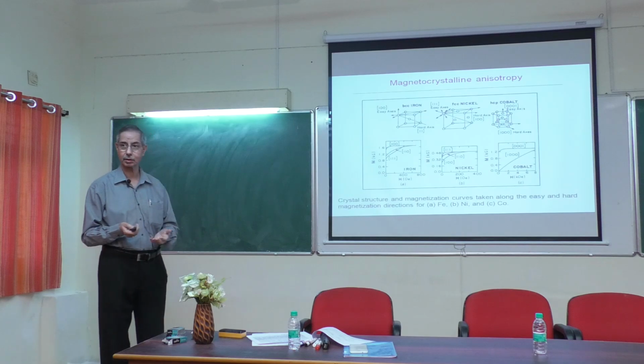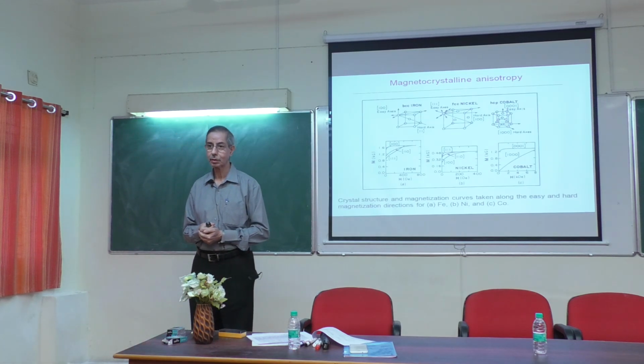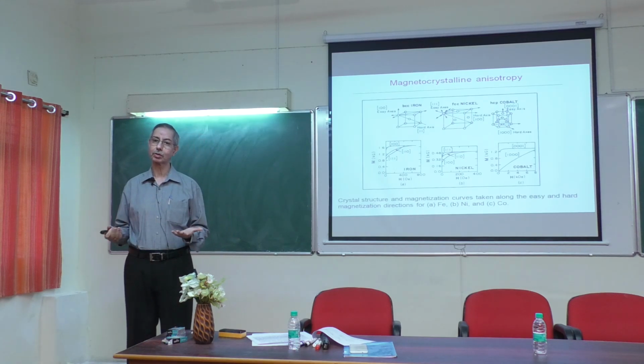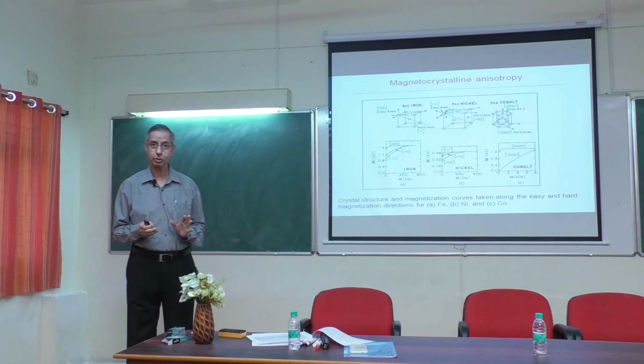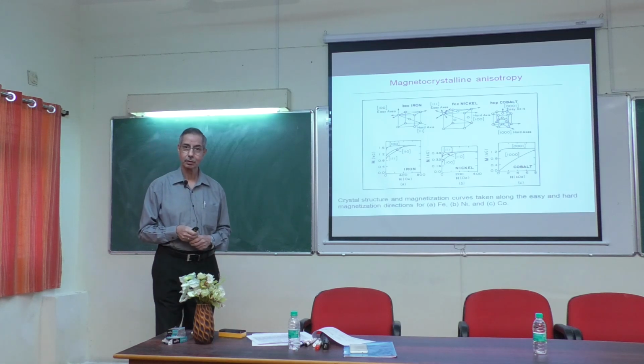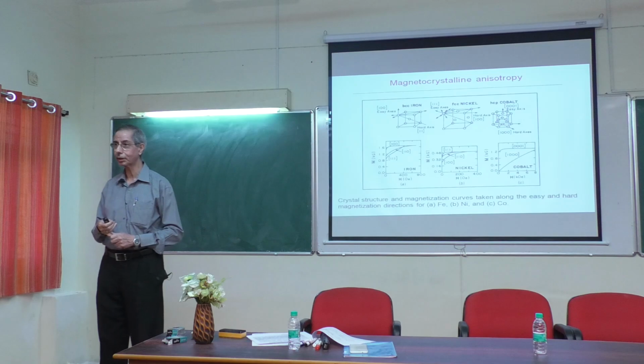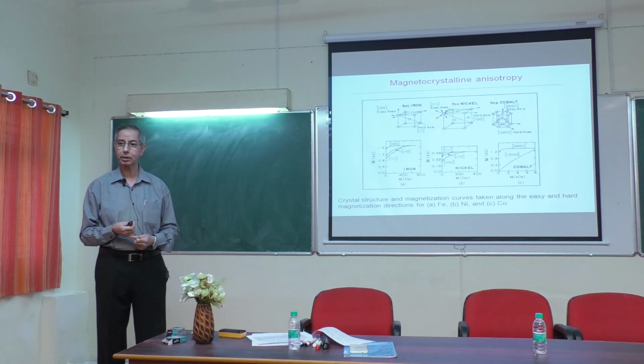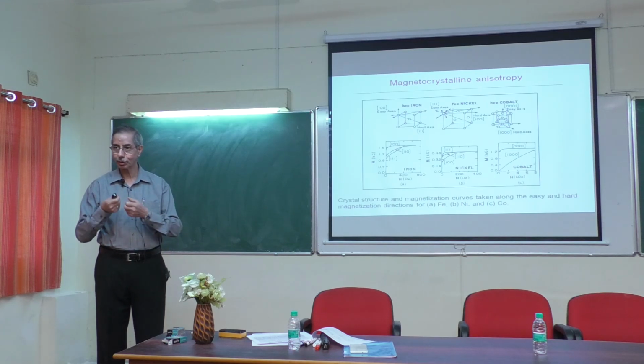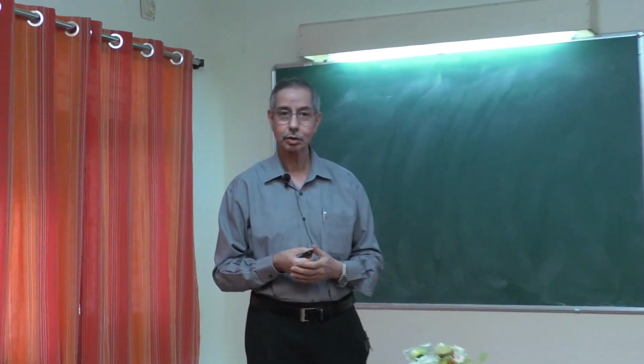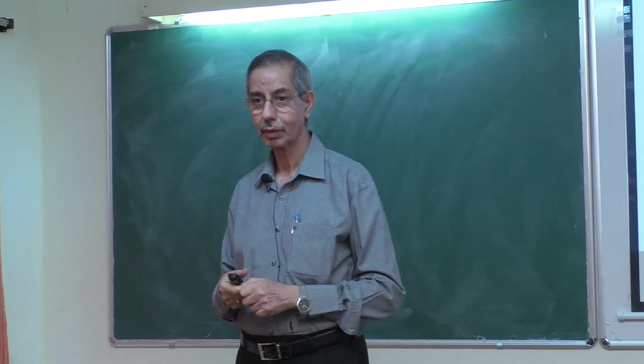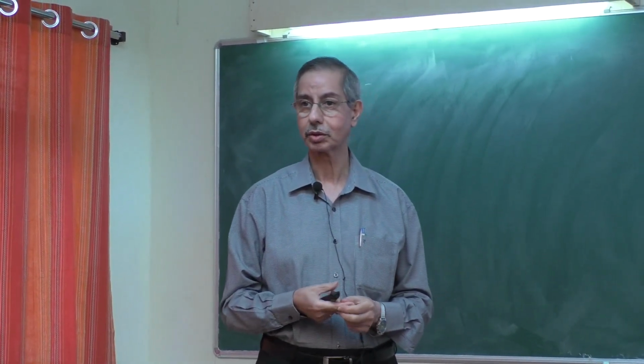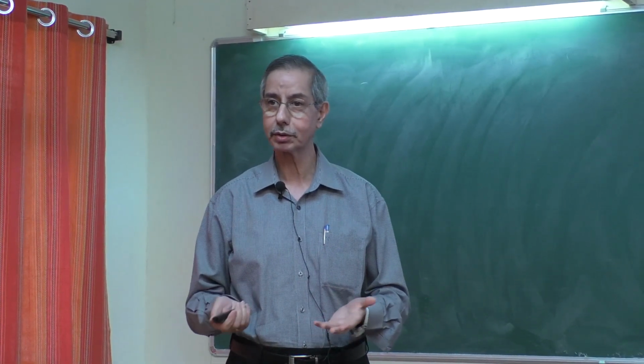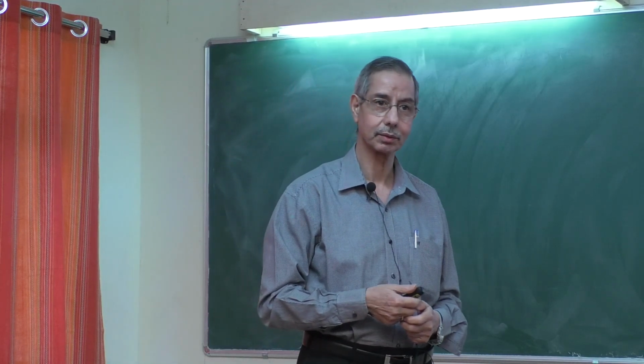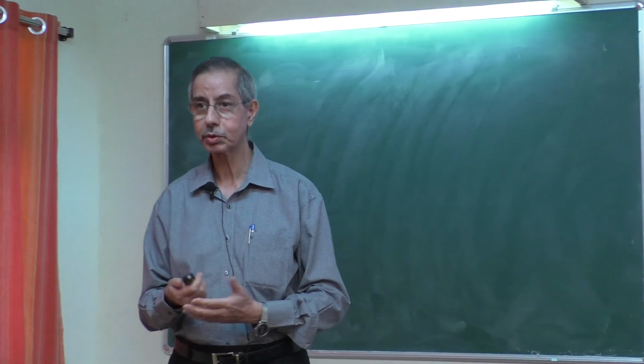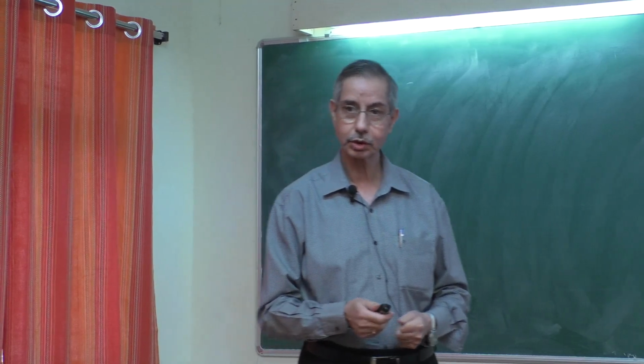Now the question is, immediately you can see there is something that makes magnetization prefer certain crystallographic directions in the absence of any external magnetic field. So something is holding them in that particular direction. Obviously, if magnetization is preferring a certain crystallographic direction in the absence of an external magnetic field, that would mean there should be some effective field holding magnetization in that direction. Now that effective field should arise from what? Should arise from some sort of magnetoelastic coupling, right? Because there has to be some coupling between spins and the lattice. Otherwise, there is no reason why magnetization should prefer a crystallographic axis as easy axis and lie along it. So this is obvious from this itself.